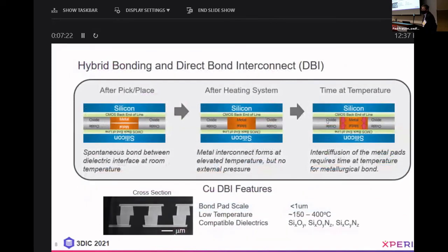And this slide shows something we're all pretty familiar with, the hybrid bonding process, where we have first an oxide to oxide bond with recess of the metal. And then after heating, the metal expands and pushes in from each side, giving a thermocompression bond with no need for applying external force. And the good thing about this is, as we've been hearing this morning, it's scalable to 1 micron or below for pad size. It can be achieved over a temperature range. We've demonstrated the temperature range of 150 up to 400 degrees, depending on the design of the parts, the design of the DBI structures. And then it's compatible with a number of different dielectrics, silicon dioxide, silicon oxynitrides, and SiCN as well.